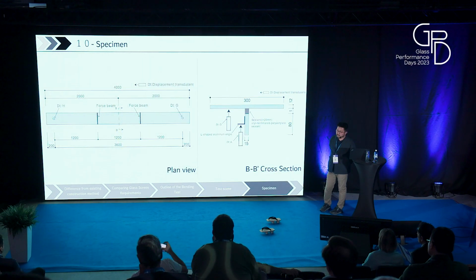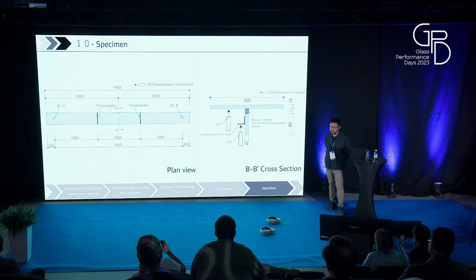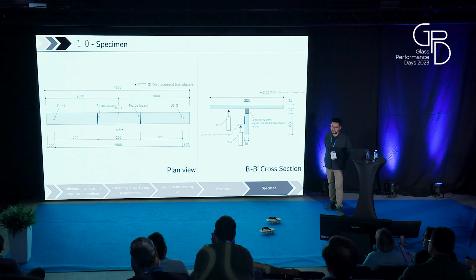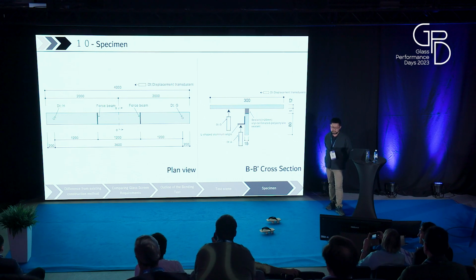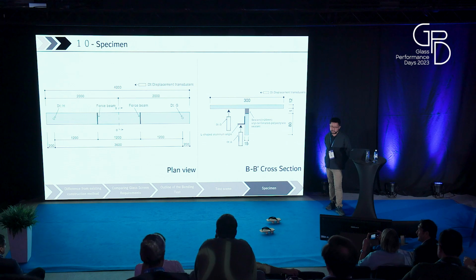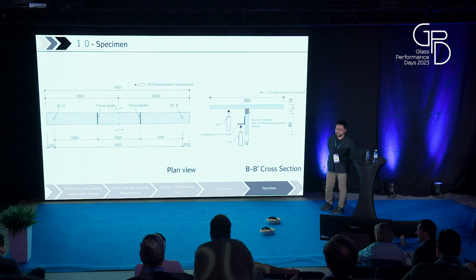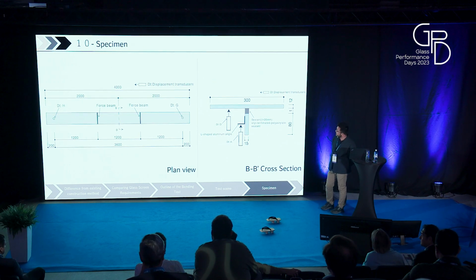Okay. The thickness of the sealant is 20 millimeters, and the sealant used is silyl terminated polyacrylate sealant. The dimensions of the slender glass stiffeners are 80 millimeters times 3,000 millimeters times 15 millimeters. And the dimensions of the glass are 300 times 4,000 times 12 millimeters.